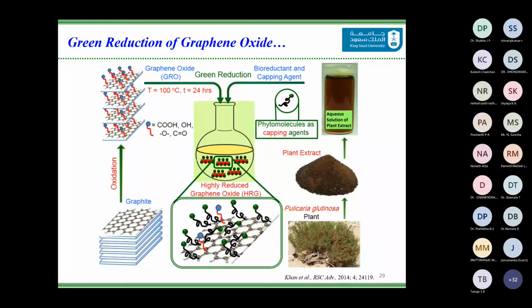However, this exfoliation gives a graphene oxide, but there is one more step that is required. That is, first you remove the oxygen containing groups from the surface of the graphene chemically, and then you add these metal nanoparticles. However, in our study, we prepared graphene oxide chemically, and we tried to reduce graphene oxide in situ, as well as the silver, the metal salt, in some cases, and in some cases only graphene oxide. So as of now, I will just talk about how we have reduced graphene oxide, and later we will see how we have added nanoparticles.